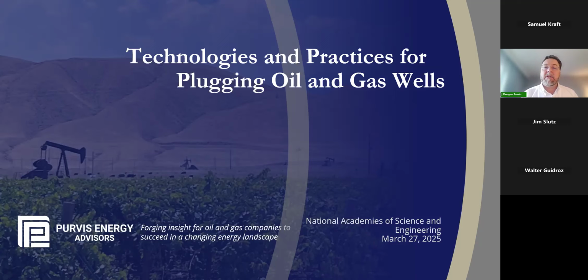The best data set that I know of has to do with the reporting in Canada of surface casing vent flow. British Columbia allows self-reporting. Alberta, as I recall, requires independent reporting. But surface casing vent flow is a measure of the failure of the cement in the annulus. And as I understood those studies, it was on the order of a quarter of the hundreds of thousands of wells in Canada demonstrated surface casing vent flow, suggesting the most common, if low volume, leak is a microannulus around that cement.